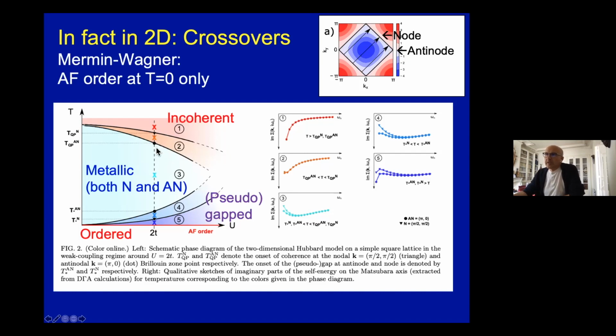And the reason being that in reality, the nodal regions of the Fermi surface, which in this case is very special and fully nested, the nodal region and the antinodal region, because of the existence of a Van Hove singularity at the antinode, actually do not reach coherence exactly at the same temperature scale. The antinodal point reaches coherence at a lower scale than the nodal region. And similarly, the antinodal region gets gapped first as you cool down. So this is why these crossovers are now opened up into two crossover lines.